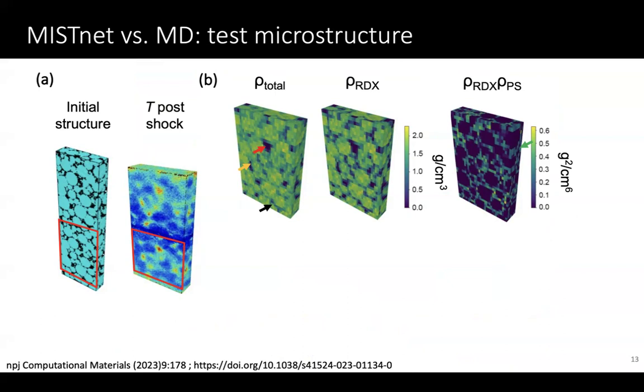And our three descriptors for the initial microstructure are total density, the density of the molecular crystal, and the product of the density between the crystal and the polymer, because that highlights interfaces. And so you can see some interesting features from the initial microstructure. There's a big void here. There's a void, elongated void here. There's another elongated void here, but it's at an angle, okay? And there's an interface here that you can see highlighted.